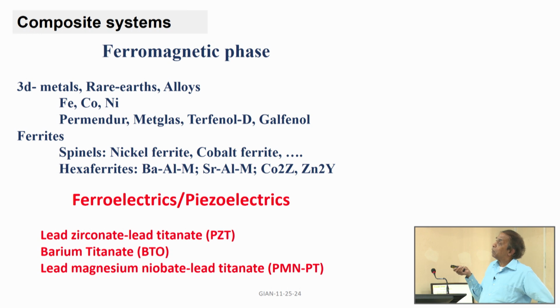So, for the ferromagnetic phase in a composite, there are quite a few choices. There are really hundreds of them. In this talk I am going to discuss composites with 3D transition metals, iron, cobalt and nickel, and rare earths and alloys. For alloys, we will discuss permendur, which is an alloy of iron, cobalt and a small amount of vanadium. Metglas is an amorphous alloy with iron, boron and a variety of materials. Terfenol-D is a rare earth alloy. Galfenol is iron and gallium. Terfenol-D and Galfenol have very good magnetostriction, and they are rather preferred materials for use in a composite for the ferromagnetic phase.